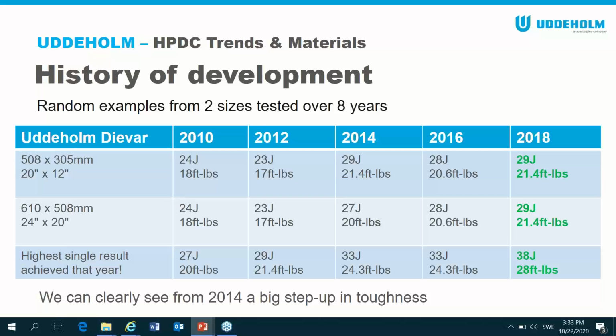So these are standard sizes. If we look at the 20-inch by 12, in 2010, we were averaging around about 18 foot-pounds on that size. By the end of the project in 2018, we were averaging 21.4. And it's the same story for the 24-inch by 20-inch. What's really interesting is if you look at the very bottom scale there, that's the highest single result we achieved that year on all sizes.